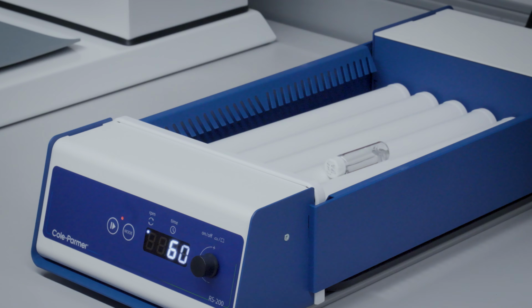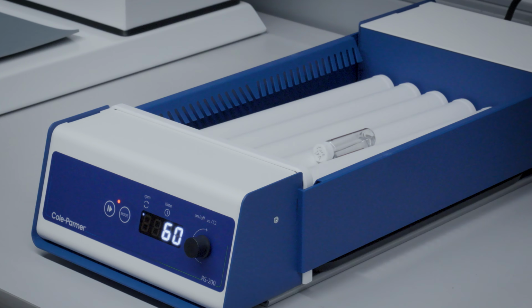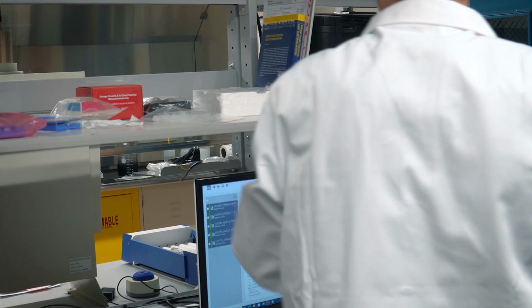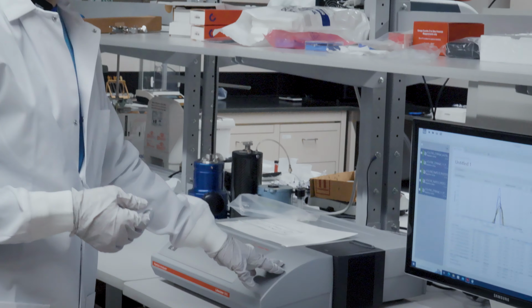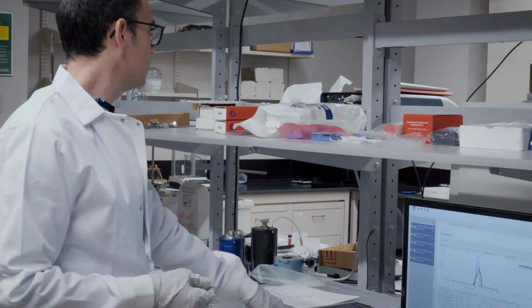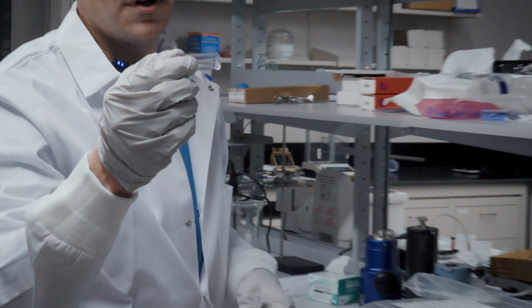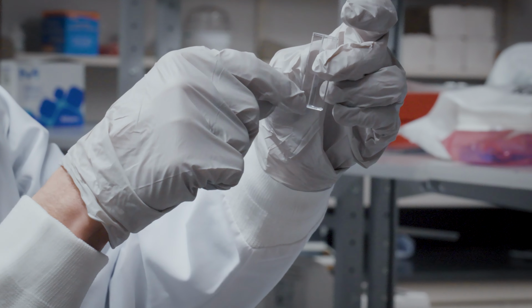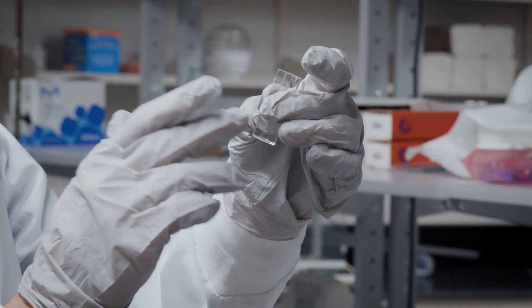So sometimes you put little balls, zirconia particles, and then between the particles they grab and crash and break the catalyst. This side here is just to answer a simple question: will this ink jet or will it not jet? So this is called a dynamic light scattering machine. What it does is you can put the ink in one of these little cuvettes, and then you can shine light, and by looking at the light that gets reflected, depending on the shift in the wavelength, we can figure out how big the particle size is.